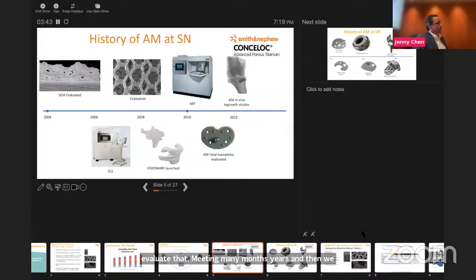We looked at E-beam, we looked at laser, and we selected the best machine we could at the time that was available. And we've since added to that machinery. And you can see there, we did animal models. We have a subarticular model that we use where we actually implant that in sheep. So we get a loading effect on the disc that is beneath the subarticulation of that sheep. And then we harvest that to see if bone grew into it.